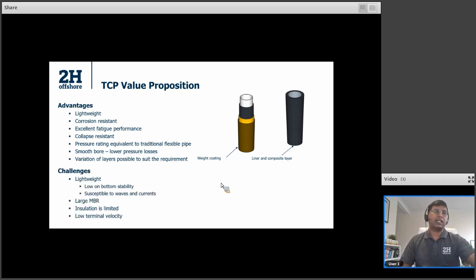But there are also challenges associated with this. While lightweight is an advantage at one stage, it could also be a bit of a challenge in other scenarios, especially in shallow water conditions, where on-bottom stability cannot be achieved easily. You might have to either use a weight coating layer, or you have mattresses to provide that stability. And also it's more susceptible to waves and currents, which is not desired for flow line application or riser application.